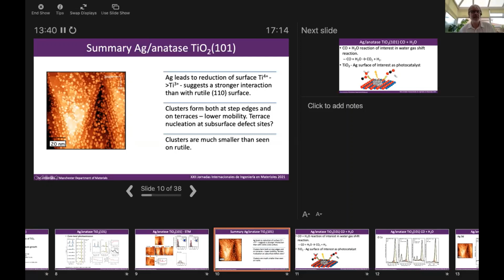These subsurface defects can be resolved in STM, and Ulrike Diebold's group from Vienna have done a lot of work on that. The final thing is that the clusters were much smaller than those seen on rutile, about half the size. So again, this is possibly due to the fact we're getting more smaller clusters forming across the terraces and eventually on the step edges. That was the basis for the silver dosed structure, which might help us understand what's happening when we actually try and do a reaction.